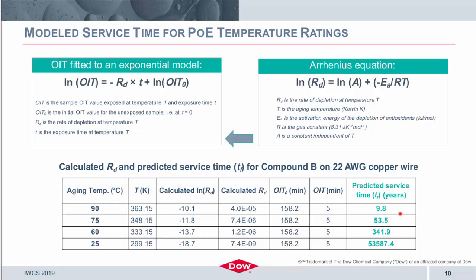Now, as we look ahead at 90 degrees C and beyond, you see predicted calculations roughly around 10 years, which is still very long, again, given the fact that you're talking about a continuous, let's say, 90C operation, which is not generally the reality of installed cables. But nonetheless, gives you the basis for being able to design not only the materials, but ultimately cables and meeting various estimated or desired service times for use in the field.